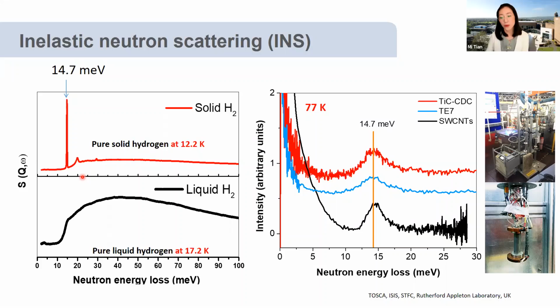Then we bring the temperature up to 17 Kelvin. Then the solid hydrogen melts to the liquid phase. The sharp peak becomes a broadening, let's say it that way. The sharp peak broadens to a big lump here. And if we continue to heat up the system to gaseous hydrogen, we just get a completely flat curve. So all the peaks and lumps disappeared.